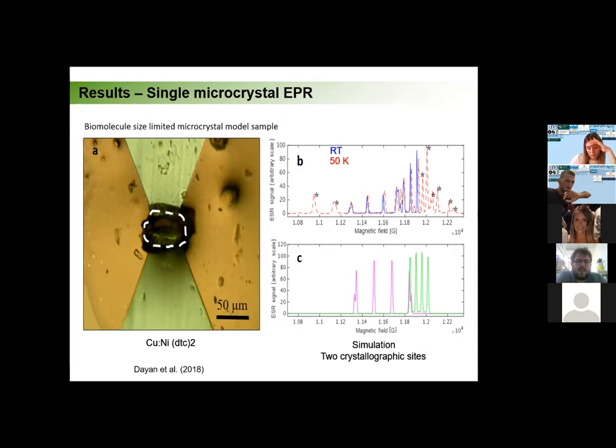Now I'm gonna show some results. In the picture, we see a close-up of the resonator with some microcrystal on it. The reason we did these measurements is because for some samples of interest, you want to measure their single crystal spectra, and it gives you a lot of information about the electronic structure of the molecule. But you can't grow them over, say, 50 microns, so you can't measure them in the conventional EPR.